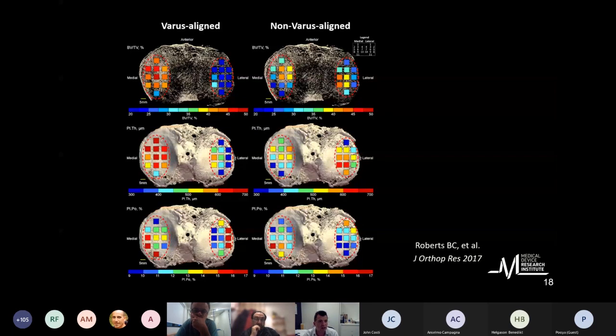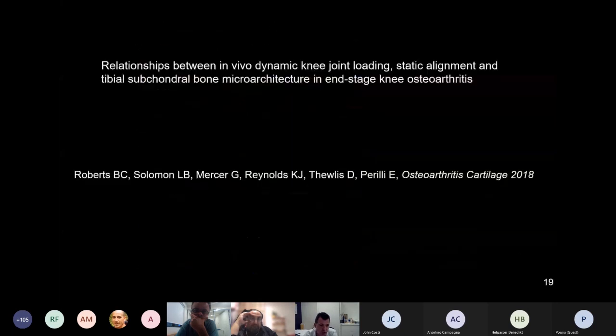Brian did a systematic mapping of this, looking at the bone volume fraction in the top row, showing in red higher bone volume fraction medially compared to laterally. We have also correspondingly higher plate thickness, so the cortex is thicker, and the porosity goes inversely to what I just said. And this is for varus aligned. In non-varus aligned, instead, we have the opposite. So that was good, but the problem is how do they work?